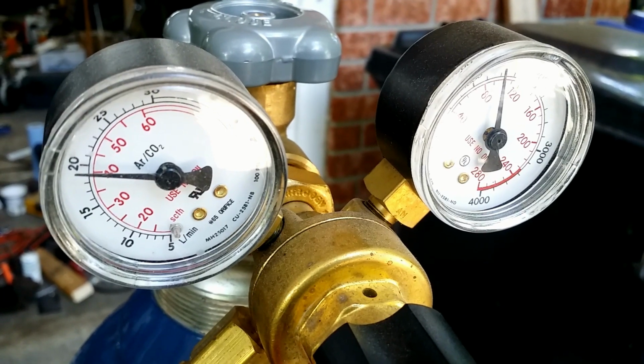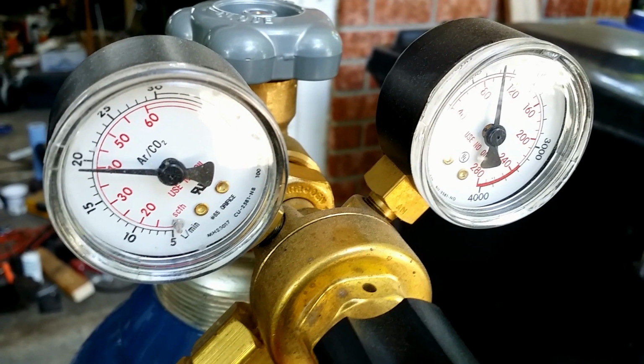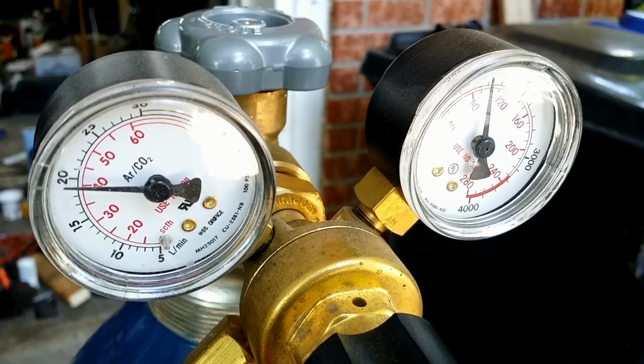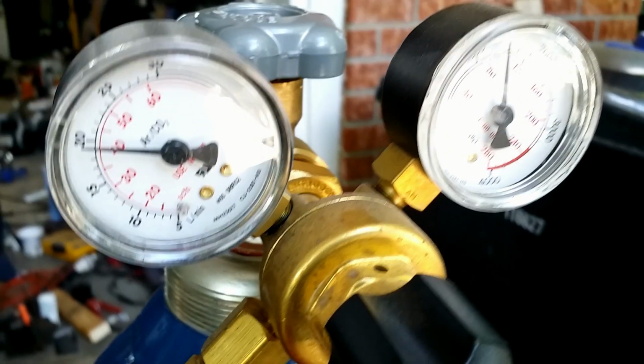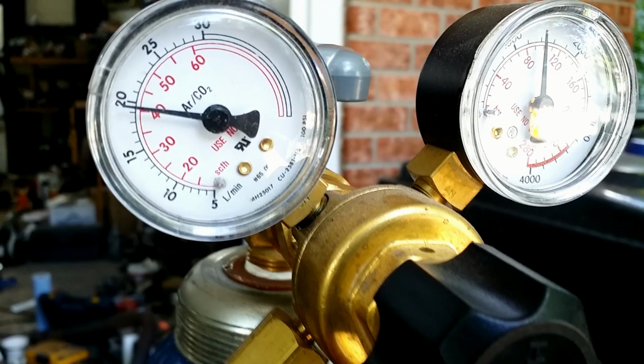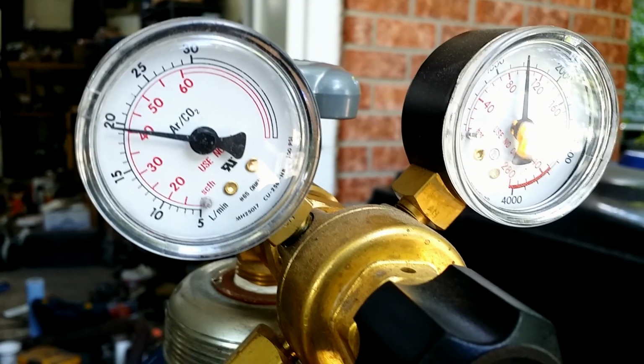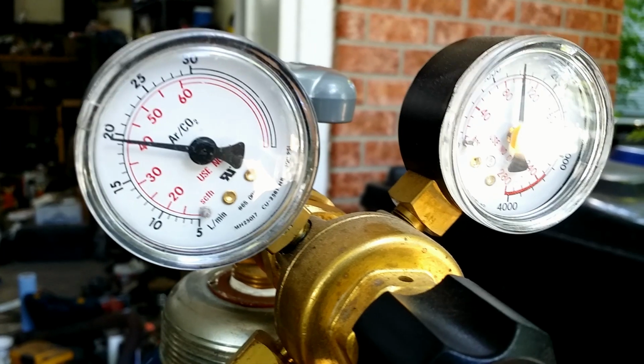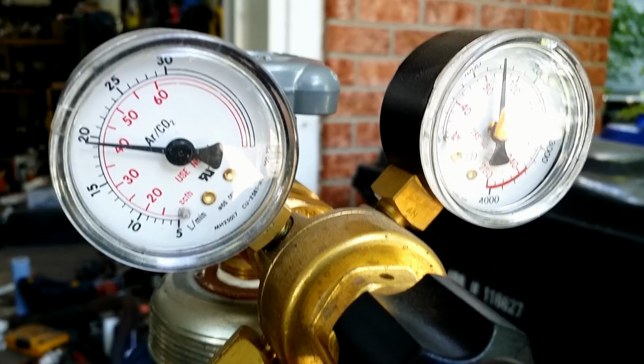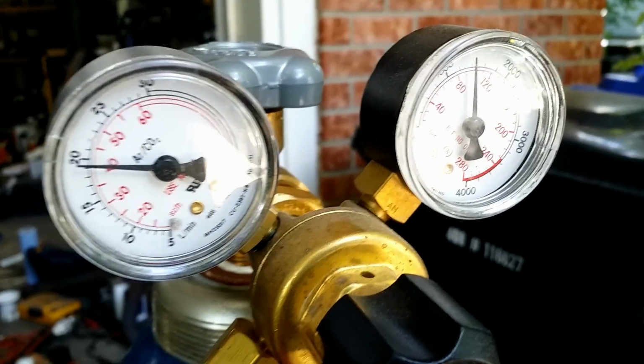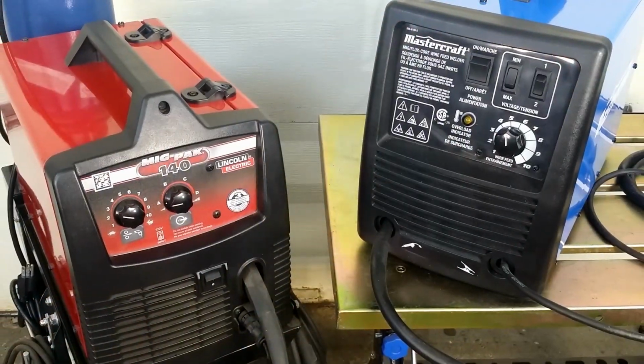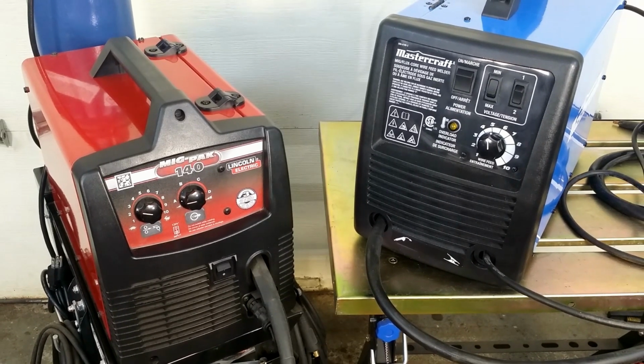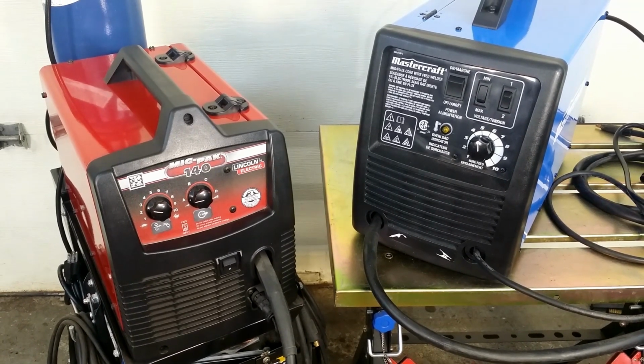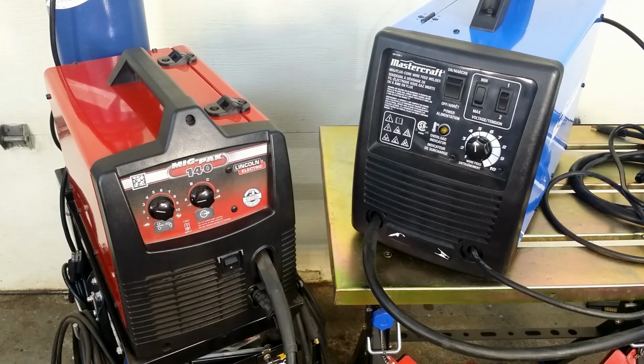But MIG welding is the process that uses inert gas, a gas that is not chemically active in the welding process. Usually it is pure argon or helium, and it is used to weld metals like aluminum. The other one is MAG welding, and this process uses active gas like CO2 or a mixture of CO2 and argon. This process is used to weld steel. So when you see that somebody is advertising his product as a gasless MIG welder, then it is an oxymoron. Same as non-alcoholic beer. You have to be really motivated to get drunk with such a beer.